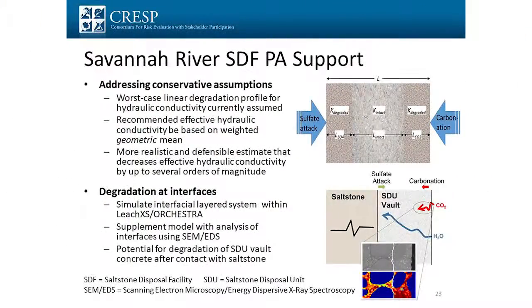I only have one slide on this. We've been doing a lot of work with Kent over the year to support the revision to the SDF, the Saltstone Disposal Facility, PA, at Savannah River. So originally they have an assumption that you have a vault and you have CO2 from the soil gas on the outside of the vault carbonating the material, and you have salt waste on the inside, sulfate attacking the material, and at some point those fronts will cross, and they say the material then, I shouldn't say magically, then becomes just like the backfill soil in terms of the hydraulic conductivity. So it's a fairly bounding assumption. I won't say conservative because David Esch is here, but I'll say a bounding assumption.